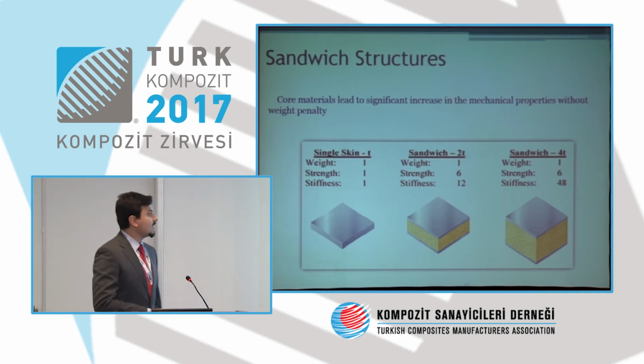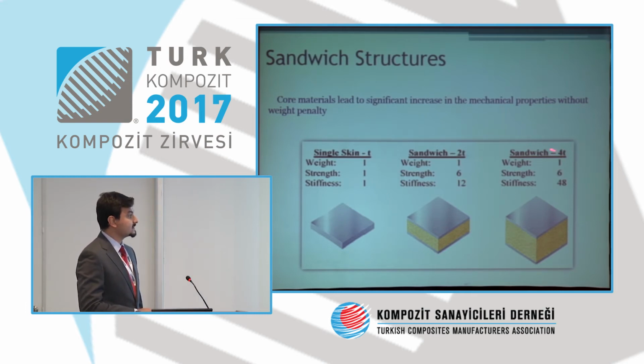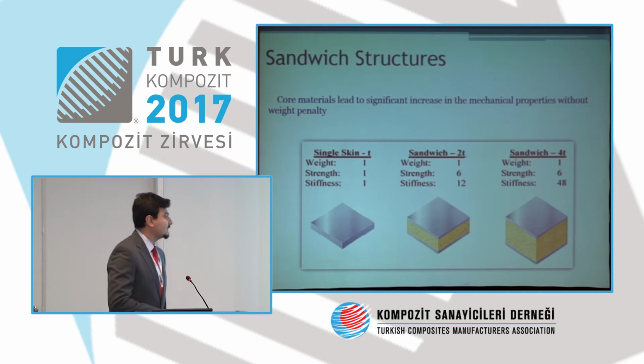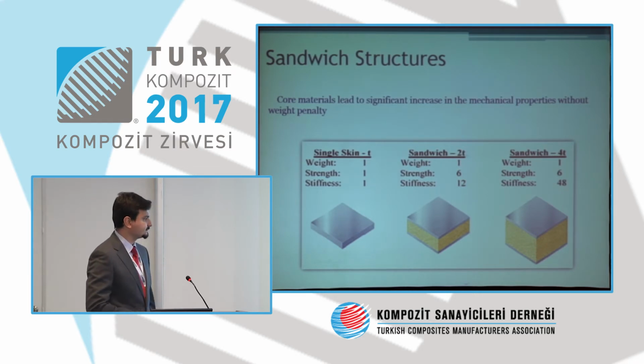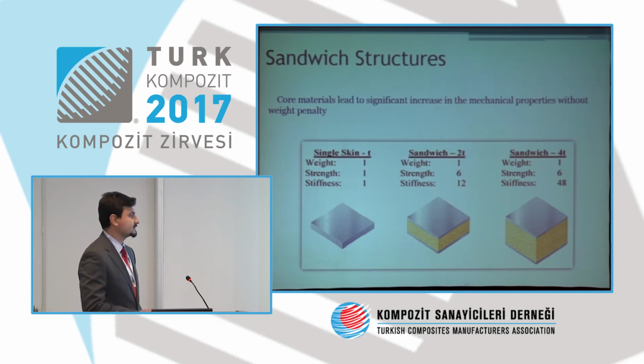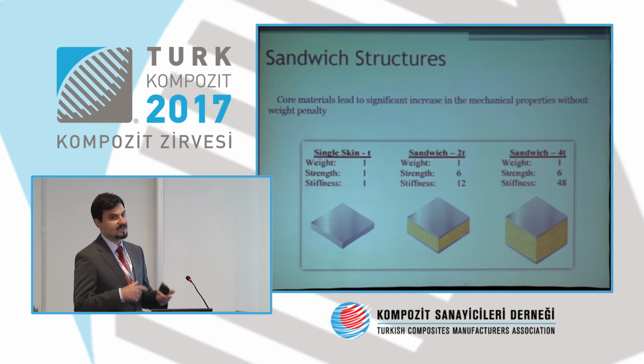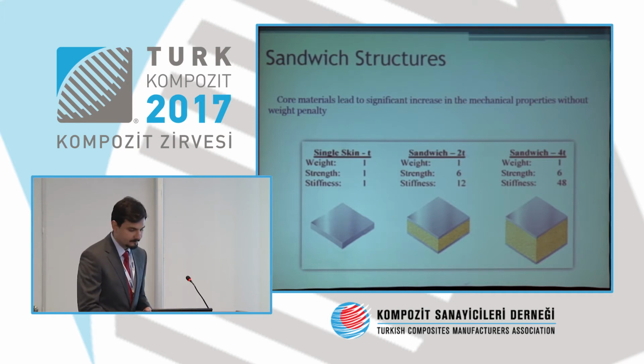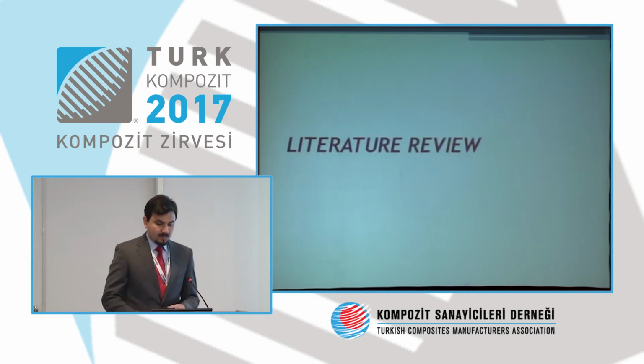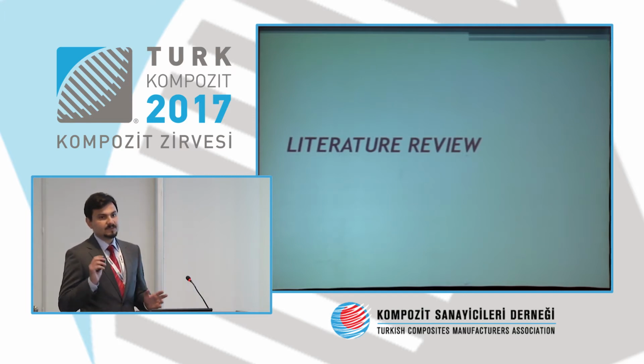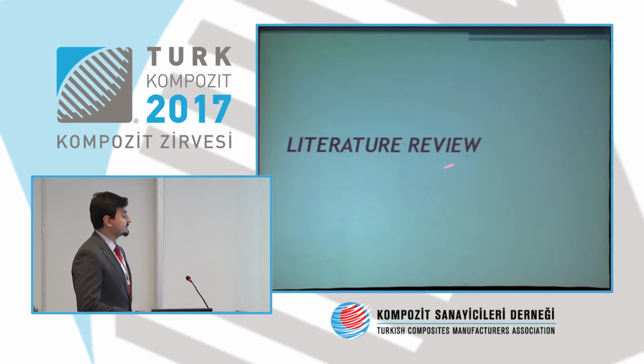times. And if we increase this to 4 times the thickness, the weight is the same, but the strength is 6 times and the stiffness increases to 48 times. This core is a very light material. They are porous media, generally. Here I will show some literature review and some papers about this subject.